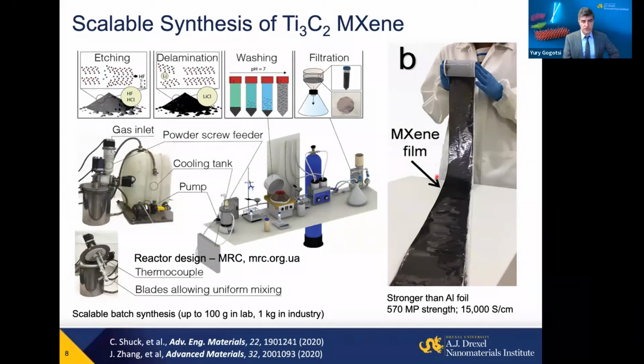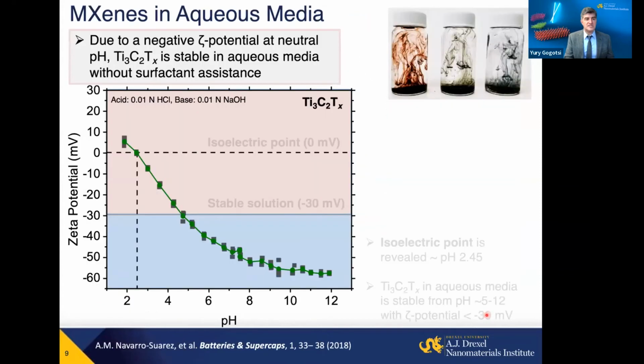And right after etching, actually, we can take a slurry of materials and, for example, by doctor blading, make a film which has strength compared to aluminum foil, high conductivity, for example, this one, 15,000 Siemens per centimeter, and process it into electrodes for batteries, supercapacitors, membranes for water desalination, filtration, gas separation, and many, many other applications there. So this is just a 1 micron film. It is supported in this case, but starting from about 3 microns, it's possible to make a freestanding film which can be handled and processed without support here.